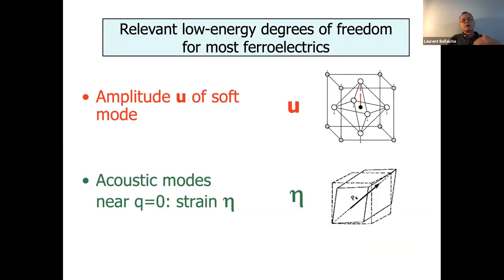So that's what effective Hamiltonians were doing in the 1990s. They selected the soft mode, which is related to polarization. And once again, it's a collective motion. This means for each five atom unit cell, you have one local mode, not five. You don't have something for bismuth, titanium, oxygen. You have something that basically incorporates the collective motions of these ions. And then you also select acoustic modes for the strain.